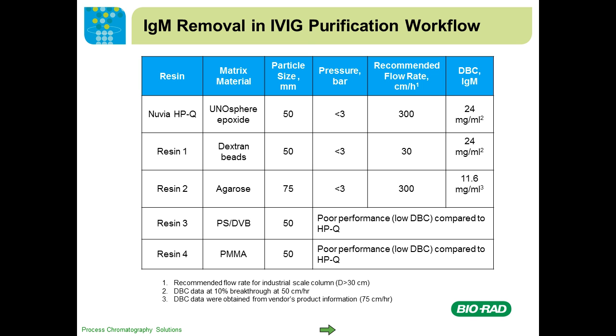For example, there's a customer who wants to use our HPQ for the IVIG purification process. One of the IVIG purification steps is to remove IgA and IgM, and they compared it with other competitor resins, for example dextran-based beads, agarose, and polystyrene beads. As you can see, Nuvia HPQ has the highest binding capacity. The dextran-based beads were also designed for large biomolecule purification, and their binding capacity is very similar to Nuvia HPQ, except the rigidity is low. Therefore, they cannot use a high flow rate in their processing.